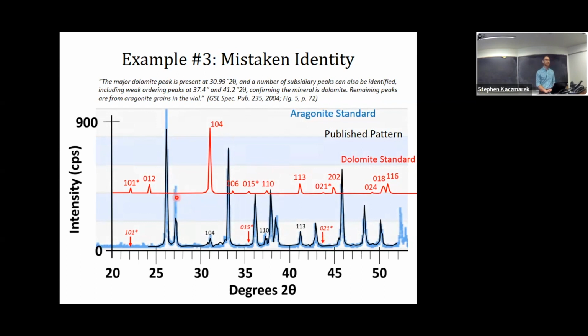So this is just a case of mistaken identity. They were looking for peaks in the 104 region around 31. They were looking for peaks in the general vicinity of 37.4 and 41.2, and they saw some peaks, but they just simply mislabeled them, and they forgot to look at their aragonite standard that they started with.